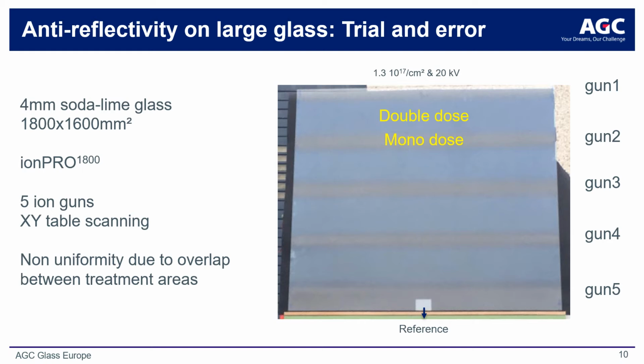In fact, it is our core competence to not only design novel surface treatments, but to efficiently scale them in a way that enables their broad adoption in the global supply chain. Ion implantation historically is not a process which is optimally suited for large area applications due to the small size of the ion beams. Here we show a preliminary effort to scale a traditionally limited area surface treatment process to a commercially practical method. The methodology in this case involves the combination of multiple ion sources situated above a moving substrate platform.